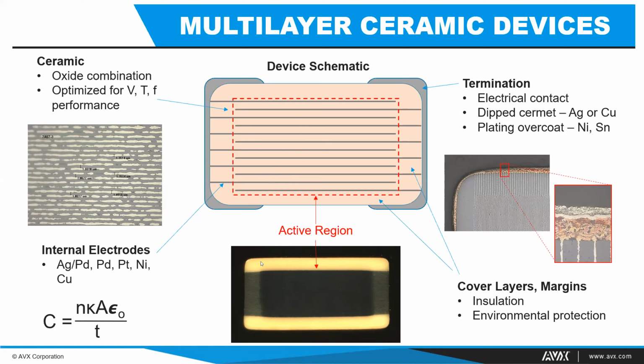get as many layers as possible into a device, and a close-up of that is shown on the left hand, where we can see having electrodes that are on the order of magnitude of the actual electrode thickness, dielectric layers that are on the order of magnitude of the electrode layers here. So something in the vicinity of 2 microns for the dielectric, and then ranging from 1 to 2 in the